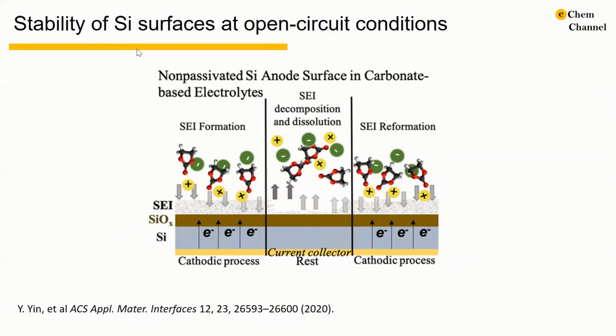On the previous slides, we talked about the SEI change during cycling. Moreover, the SEI formed on the silicon surface is not stable at the open circuit condition, which also leads to calendar aging. So for this work, they find that chemical components such as lithium alkyl carbonate in the SEI formed from carbonate-based electrolyte are intrinsically reactive on the silicon surface. A decrease in passivation and increase in reactivity of the SEI could already be observed after 1 to 10 hours. Such behavior persisted after hundreds of lithiation rest cycles and was associated with the intrinsic reactivity of organic compounds of the SEI. So overall, it suggests that the organic SEI components are unstable, either because they continue to react or because they are soluble in the electrolyte, or both.